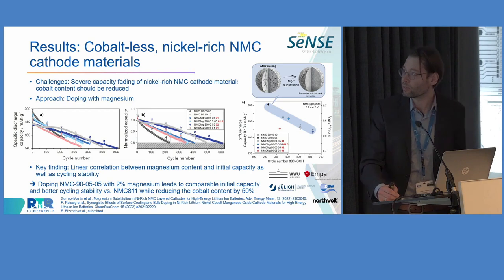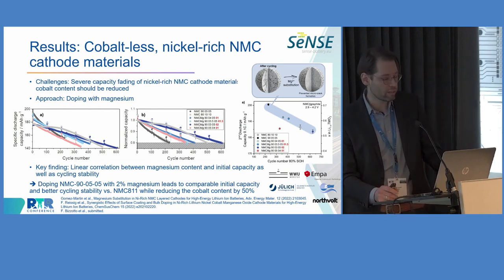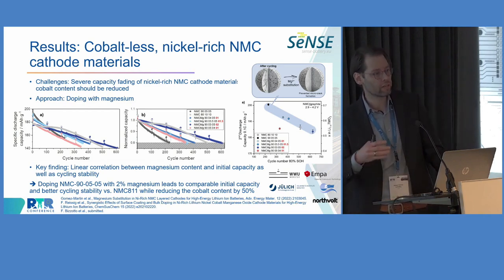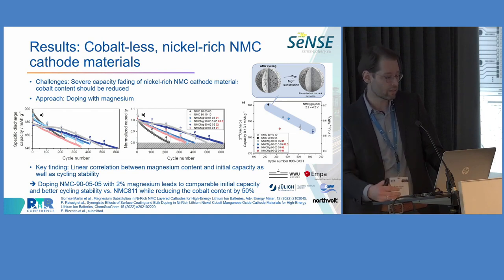Now I would like to highlight four results that so far came out of the project, starting with the cathode material. So here for nickel-rich NMC, the challenge is really when you increase the nickel content, you gain in capacity, which is nice. So in that way, you can increase the energy density. But at the same time, the material becomes less stable.